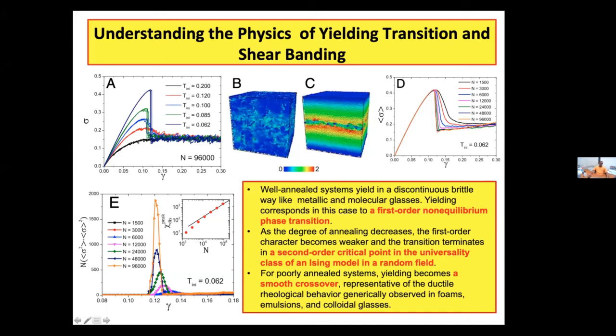And so if you look at the glass that is prepared at high temperature, at the initial temperature of 0.2, then you do not see any sharp overshoot in the stress versus strain. And this kind of yielding is more reminiscent of ductile yielding, which is represented in panel B. And if you look at the stress-strain curve for temperature 0.062, you have a very sharp drop. That is reminiscent of brittle-like failure, which manifests itself via shear band formation, depicted in panel C. And this has been claimed to be a non-equilibrium first-order phase transition. And to support it, these authors also looked at the stress-strain curve as a function of increasing system size. And it seems that as you go to larger and larger system size, the drop becomes extremely sharp.